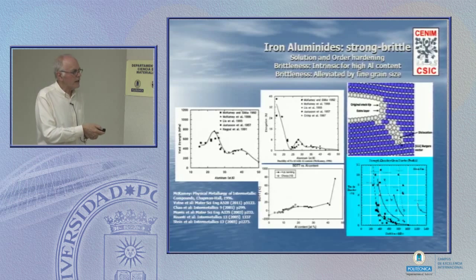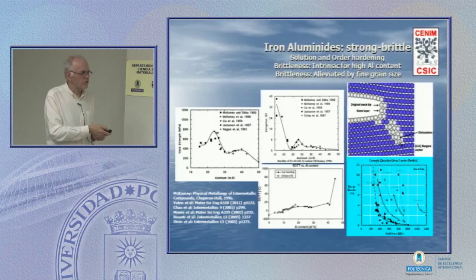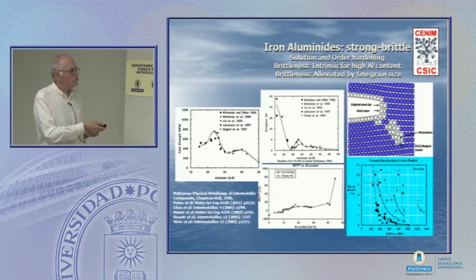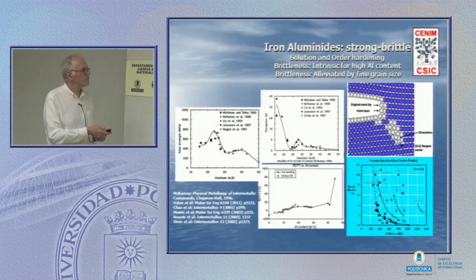Here, each of these lines defines the ductility-strength envelope for material of a given grain size. If I go from something like 100 micron grain size to 10 micron down to 1 micron, I push the envelope up diagonally to higher strength for the same ductility.